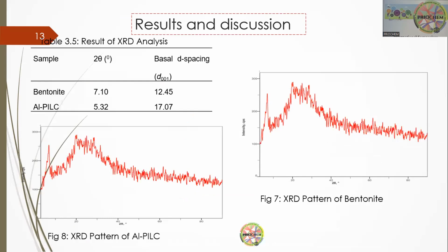So here is the result of the XRD. As explained in the introduction, our target is to increase the surface area. You cannot increase the surface area until you increase the d-spacing. So you can see here, from the basal d-spacing of 12.45, we are able to increase it to 17.07. There is a shift of the 2 theta value a little bit backward, from 7.10 to 5.3. So this has confirmed that we have increased the spacing.